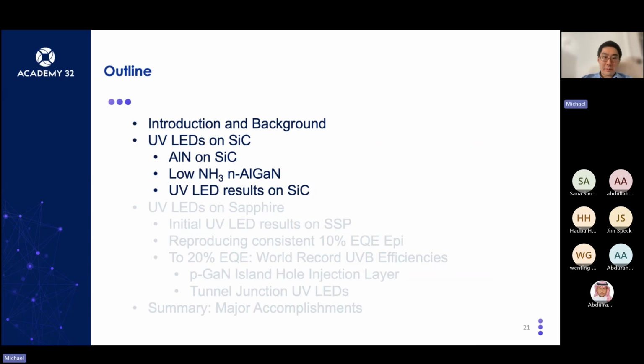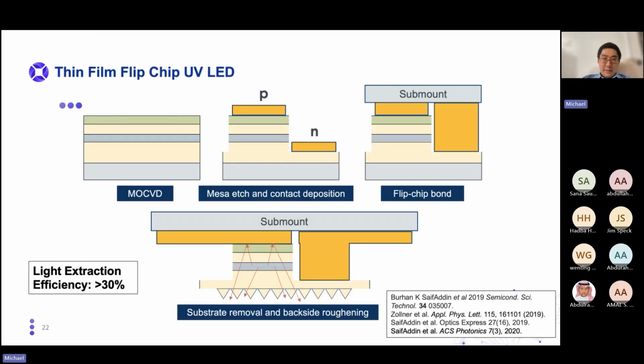So going off of that, we worked on the UVLED epi on silicon carbide, and this is the main idea of using silicon carbide, that we can remove the substrate to extract the light from the device. So we first grow our device in MOCVD, so this is silicon carbide, this is n-type AlGaN, this is our quantum wells, this is the p-type, and this is a p-type gallium nitride for hole injection, because our p-type aluminum gallium nitride is very resistive.